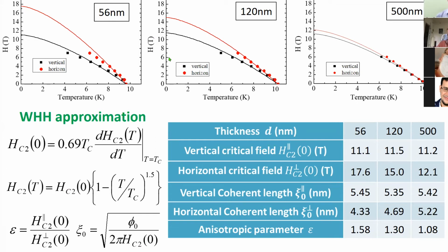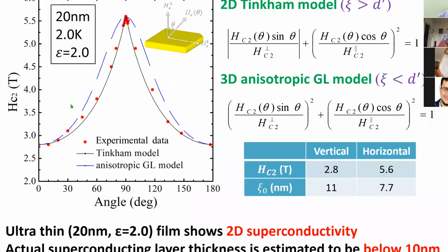So using this plot, in a thin film less than 20 nanometers, we plotted HC2 like this. In this case, there are two models to explain these tendencies, because this is the angle for the magnetic field that we applied, and we can see this shape.